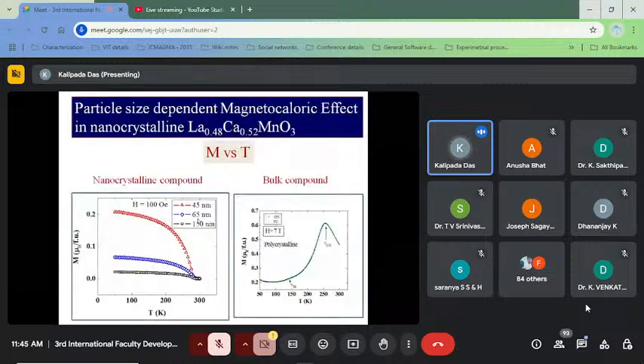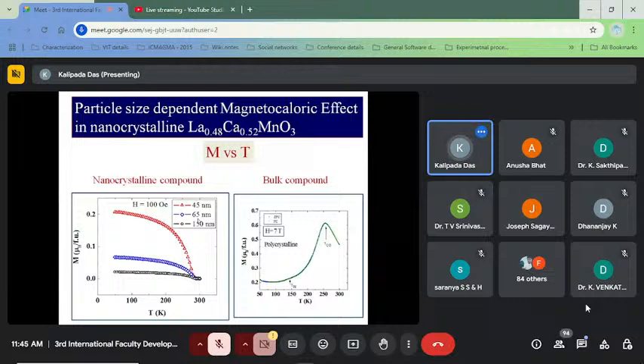Now, for the 52% doping sample, we have compared the magnetization as a function of temperature in the presence of a very low magnetic field. In the case of 150, magnetization is slightly lower, and for 65 it is enhanced, and for 45 nanometer it is enhanced and the ferromagnetic ground state is pronounced. And comparing one by one, here the response of the bulk sample is given, and we see that antiferromagnetic type ordering is there. This is the charge ordering, and this is the antiferromagnetic ordering.